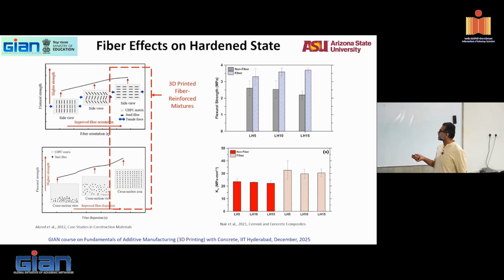In the hardened state, again, you see here fiber dispersion, how the fibers are distributed when you're testing in flexure. If your fibers are in this direction and you are bending it in this direction, these fibers arrest the cracks, and therefore the flexural strength will be higher. Whereas if you are in this direction, cracks can really go in between fibers, so you really have no increase in strength.